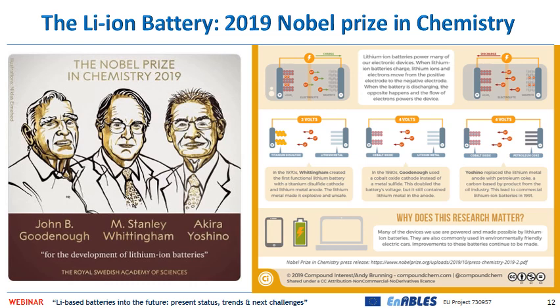The key components are intercalation or insertion electrodes that can reversibly store lithium in the form of ions, and the electrolyte, which plays a key role physically separating the two electrodes and allowing ions to move back and forth. When a lithium-ion battery is fully charged, all the lithium ions are stored between the layers of graphene in the graphite electrode, the anode. They have all moved over to the right on top here. In this charged state, the battery is effectively a multi-layer sandwich where graphene layers alternate with lithium-ion layers.